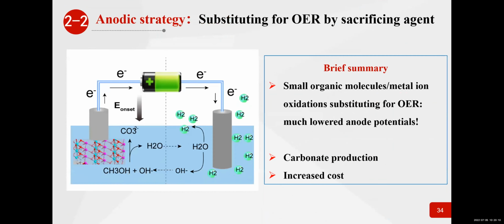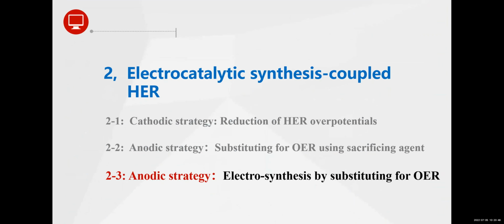So a previous study shows that small organic molecules can be used as the sacrifice agents to substitute for OER. In this way, we can achieve much reduced overpotentials and much reduced energy consumptions. However, in this experiment, we use the sacrifice agents, and then sometimes we can obtain carbonate. This kind of product will impede the continuous electrocatalytic process. So next, we tried to have some electrosynthesis at the anode. Not only substituting for the OER, we can also get some valuable chemicals by the oxidation at the anode of some kind of small organic molecules.